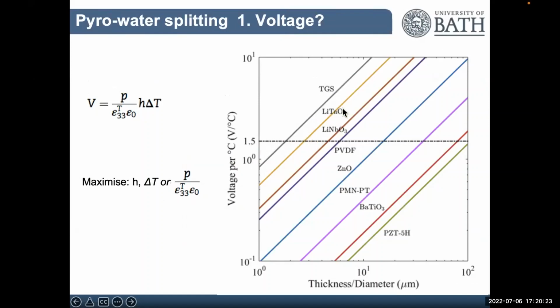So you need to see that lithium tantalate, lithium niobate are good. Surprise, surprise, these are used in thermal detectors. PZT, the material I used, is not very good actually in terms of voltage because of the high permittivity. But actually, I still only need 100 microns as a device to generate that 1.5 volts for 1 degree C. So for voltage, PZT is not great, but even a thin device will do it.